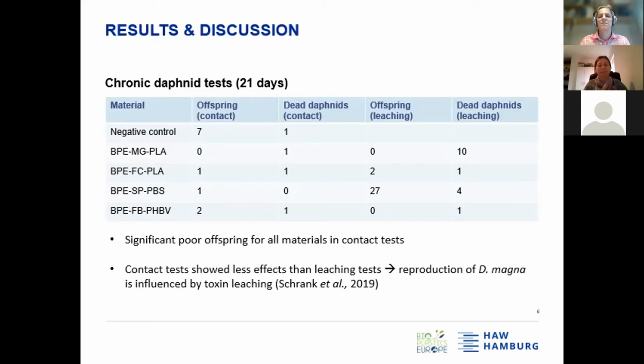And this could be explained by the sample preparation, because during the shaking process of the plastic material in the medium, the pollutants from the material migrate to the water phase, and so they become more bioavailable for the daphnids. And this is in accordance with a study from Schrank in 2019. So there the reproduction of Daphnia magna was also influenced by toxic leachates, not by the plastic itself, but by the leaching compounds of it.